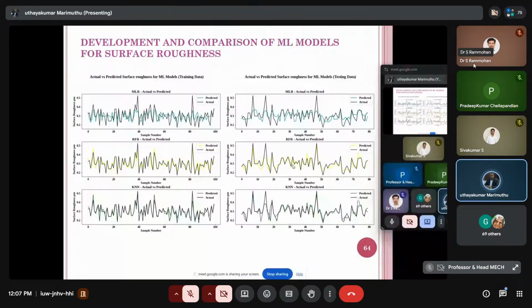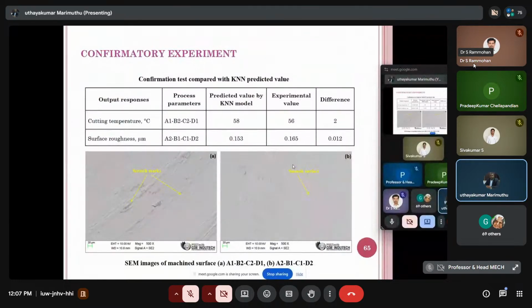The potential applicability should be witnessed by how much accuracy is projected in the real-time application, compared with the real-time application. This is about the confirmation experimentation. This confirmation test was compared with the KNN predicted value. This is the output response for cutting temperature and surface roughness. A1, B2, C2, D1 are the parameters of the Taguchi design. Then predicted value by KNN model 58, experimental value 56, difference is 2, and the surface roughness is similar. And the corresponding images of the machined surface are shown according to this condition.